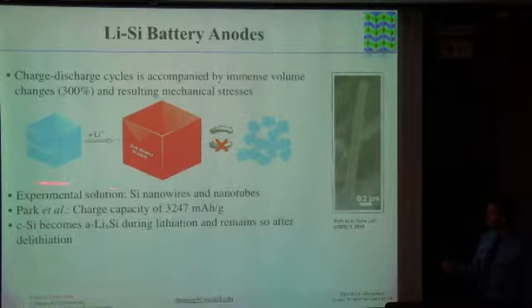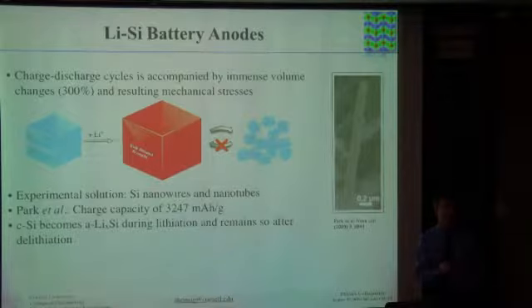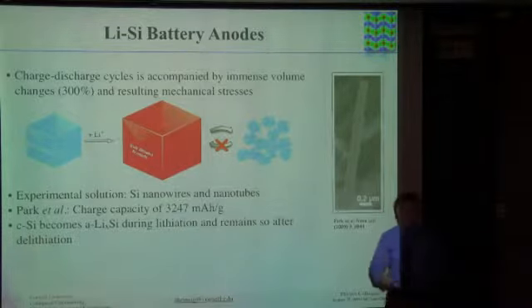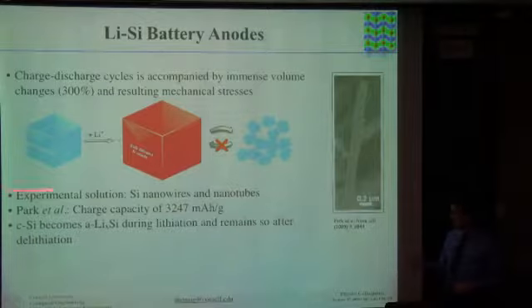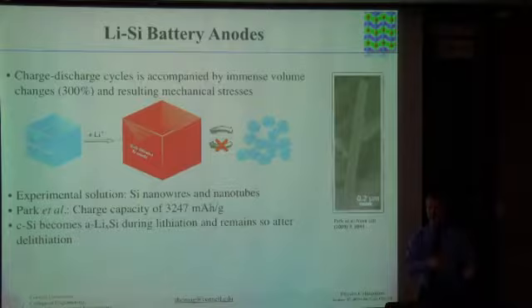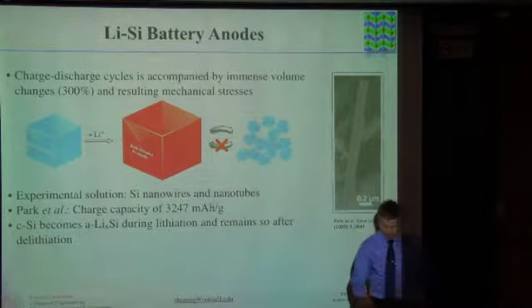So here's the work by Park and Cui and co-workers, which showed that these silicon nanowires can have capacities of about 3,000 milliamp hours per gram, about a factor 10 larger than current materials. So that's great. The one thing they also observed, that crystalline silicon during lithiation becomes amorphous. So we were interested also, let's look at that energy landscape for that system. Let's figure out what structures form, what's experimentally known, what do we find in our structure search, and what happens if they were amorphous? How does it affect the energy and the power density, the energy density?